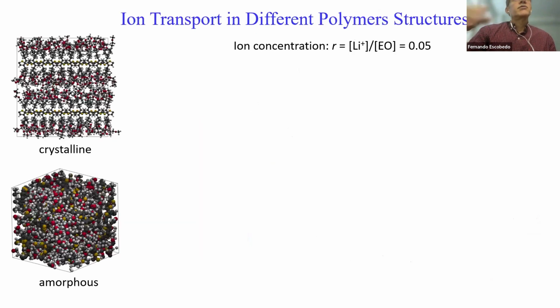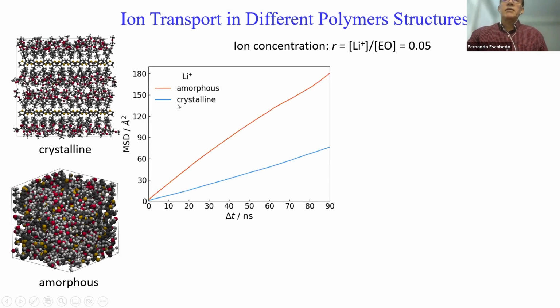But importantly, we want to understand the ion conductivity, of course. So these results are going to be for a concentration of ions of 0.05. We're going to look at the crystalline and the amorphous system. And if you look at this mean square displacement of the lithium ions, you find that it actually travels much faster in the amorphous material than in the crystalline material.